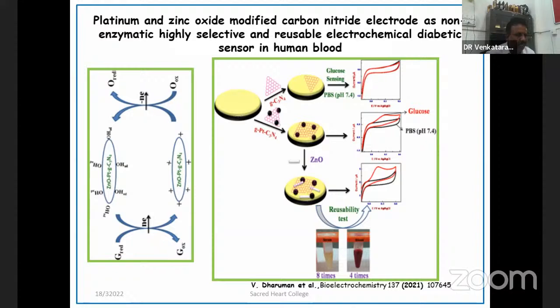By applying the carbon material along with metal oxide, we are able to reproduce in whole blood. We can get the signal only 4 times, whereas if you use serum, we can get it reproduced more times, but still it is not enough for a market product. So we are still enhancing, because in the original glucose sensor, they use a polymer membrane to entrap glucose oxidase. But here we did not have any polymer membrane. Instead, we have only carbon nitride modified with zinc oxide and platinum, and without glucose oxidase, we are able to sense glucose in a blood sample.